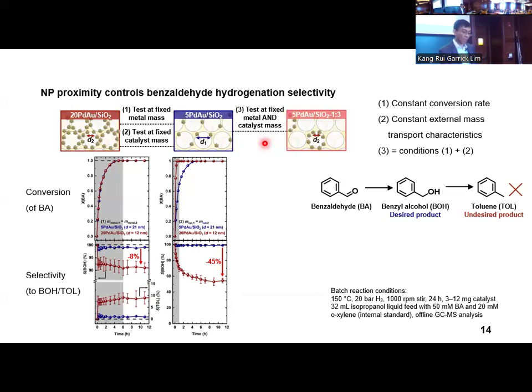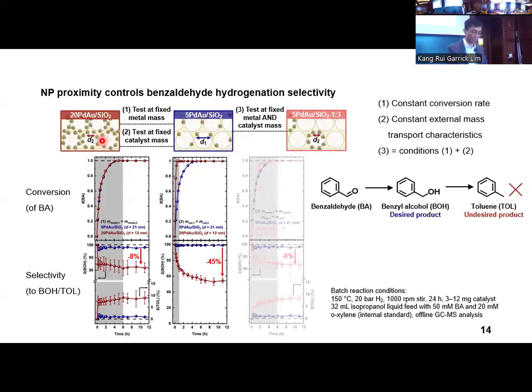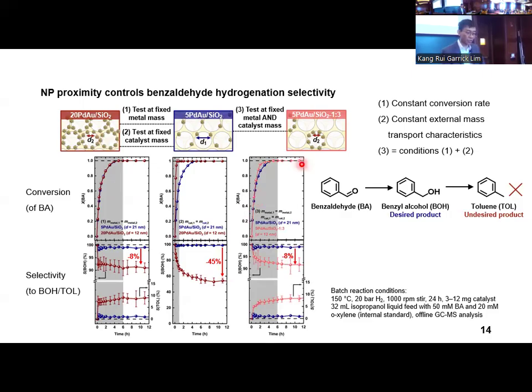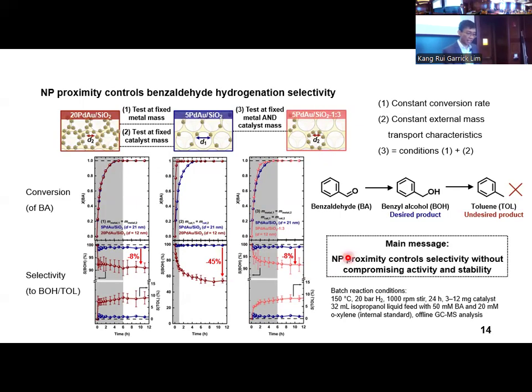Finally, we maintained both aforementioned conditions simultaneously by comparing the locally high metal density catalyst against a regular 5 weight percent catalyst. As I've mentioned earlier, the catalyst over here has the same 5 weight percent metal loading as a regular 5 weight percent catalyst, but has an interparticle distance that resembles the 20 weight percent catalyst instead. We found that the benzaldehyde catalytic activity was similar in both 5 weight percent catalysts, regardless of interparticle distance. However, catalysts prepared using raspberry colloids with a higher nanoparticle density and thus shorter average interparticle distances still displayed a lower selectivity to benzyl alcohol. Taken all together, our catalytic results illustrate that the interparticle distance independently controls selectivity without compromising activity and stability.